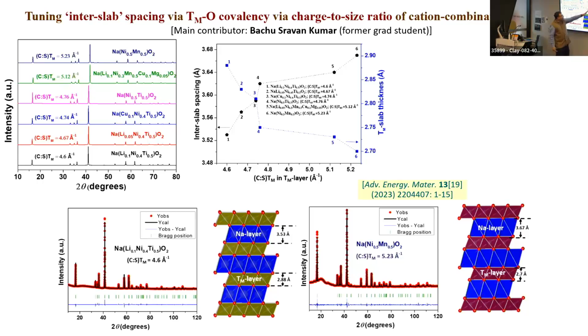So as I lower the charge to size ratio of the cation combination in the transition metal layer, my interslab spacing goes down, which indicates that my sodium oxygen bond has become smaller and stronger, and sodium ions will not find it easy to spontaneously come out of the lattice. So this one should give me the best air-water stability.